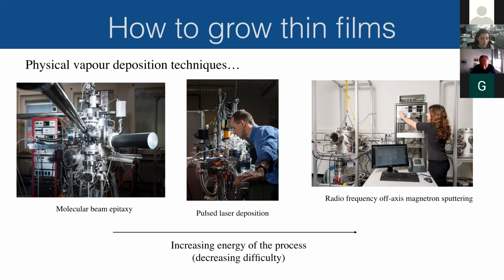Pulsed laser deposition is a bit more high energy. You have a very focused laser coming in and hitting a target, which can be a single crystal or a pressed powder, usually stoichiometric with the film that you want to grow. The laser pulse ablates the ionic species, and they go to the substrate, which is again close by in this ultra high vacuum chamber. And then the highest energy process is a sputtering process using ions, which bombard a target, again usually a pressed powder ceramic target, and the ionic species come out and find your substrate. So the energy increases along this axis, and I would say that the difficulty decreases along this axis. Molecular beam epitaxy takes a lot of adjustment to get the fluxes of the ionic species right. Here I am modeling sputtering, which is so easy that even I can do it. So you can imagine.